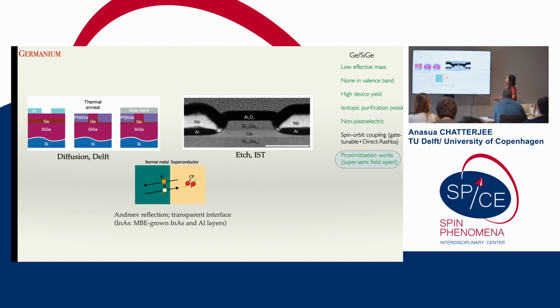So there are two ways that people are pursuing this, probably other ways, but the two ways that I'm going to talk about. One of them is, I think Georgios Katsaros at IST has tried, which is to etch away up to the quantum well and then add aluminum and niobium, which has a higher critical temperature, on top. And then the way that Giordano Scappucci at Delft actually first tried out, and it succeeded really well on the micron-scale devices, is to put platinum on top of the heterostructure and then anneal it such that platinum germanosilicide is formed and goes down and contacts the germanium. So this forms an ohmic contact. And in fact, a lot of superconductors and normal metals seem to form this kind of easy contact in germanium. So that's also nice.